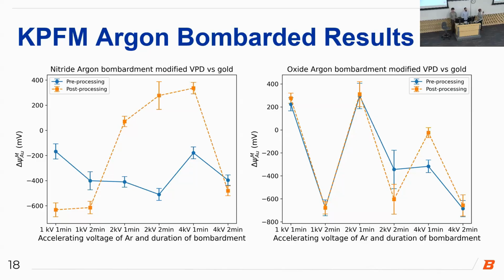So this also depends on the probe that is taking the measurement, which is what these error bars are, a combination of the error of the probes for both the standard and the sample itself. So these results should just be used for a qualitative assessment, not quantitative. All that to say, why do I have a zigzag effect on the oxide argon bombardment?